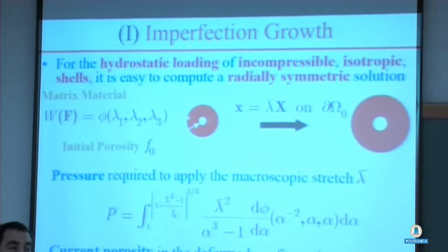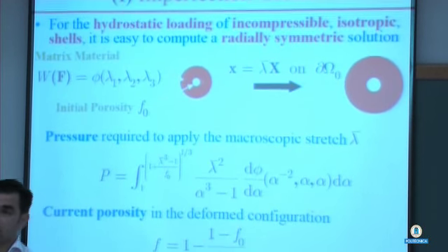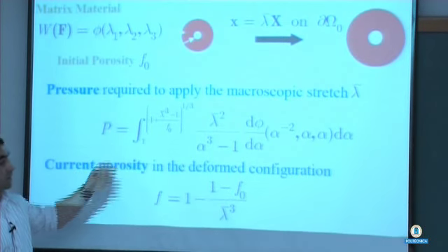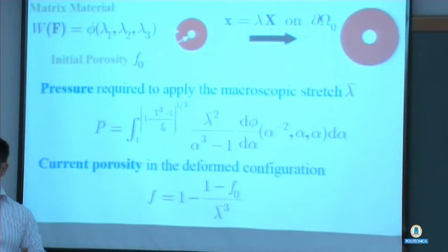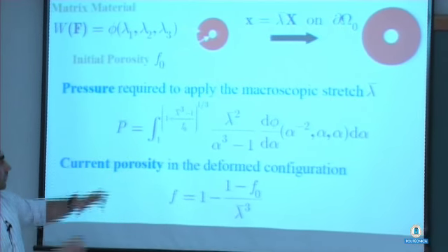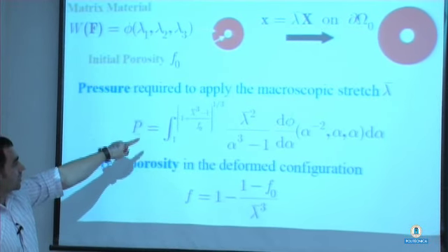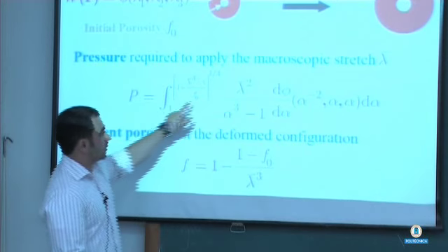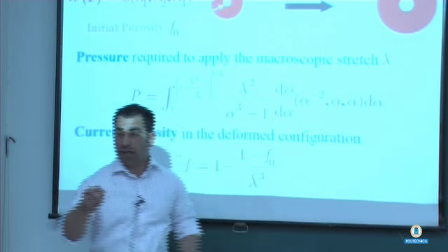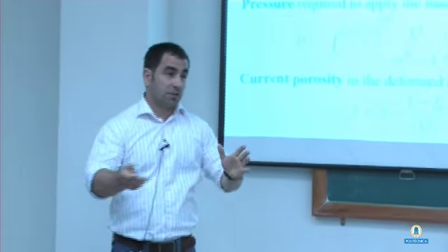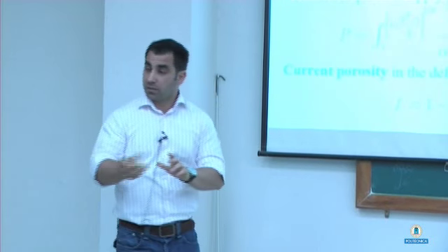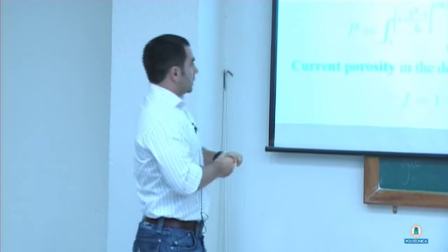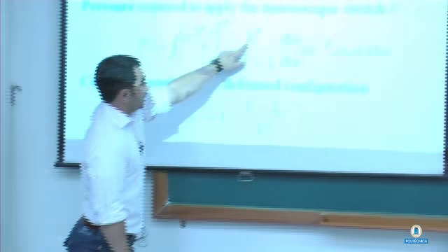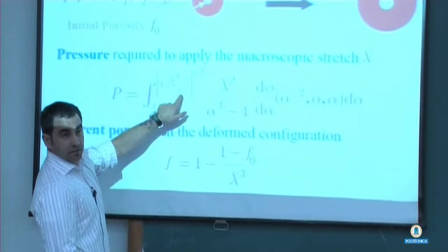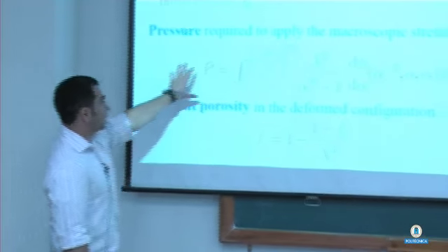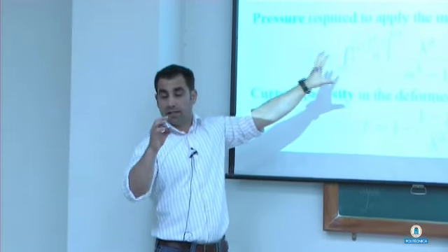So this can be solved, and you don't need to solve the equilibrium equation, which is a nonlinear one. You just need to use the fact that the material is incompressible and isotropic, and you have radial symmetry. And if you do that, the pressure that you're required to apply to the shell to deform it a stretch lambda bar is given by this equation, right? And this phi is the stored energy function that characterizes the behavior of the material. So this is for any material, provided it's isotropic and incompressible. All right, so you see here that the pressure, of course, depends on the stretch, but also on the initial porosity. And, well, that's for any shell, right? Any size of the hole.